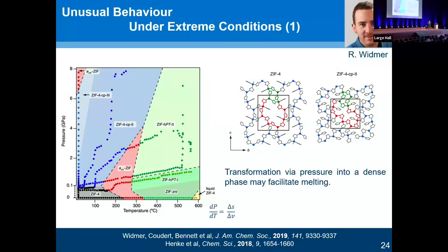Well, the two things to point out on this graph are, one, we can form weird exotic phases, right? Where we can't form them under ambient conditions. So that's pretty neat, right? New MOF discovery. And the other one is this melting slope. That's positive. Right, so melting gets harder with pressure. The reason why melting gets harder with pressure: dP/dT is ΔS over ΔV, that's the Clapeyron relation. Entropy change from solid to liquid, it's positive. Volume change from a dense MOF to a liquid is positive. So that slope's positive. Great.